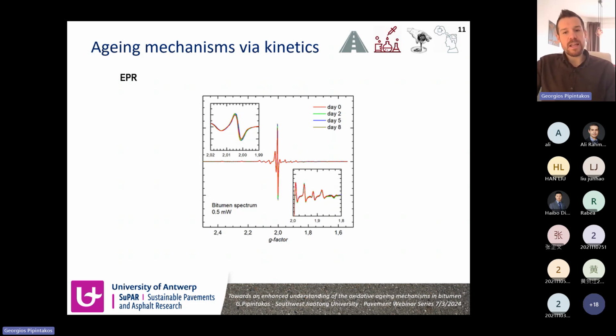Of course, there were some challenges in the beginning because it was one of the first times that this technique was used for bitumen. And we experimented a lot with the sample preparation in the beginning until we had good repeatability and also an optimized sample preparation. And here you can see one of the spectra of bitumen A, at different time intervals.